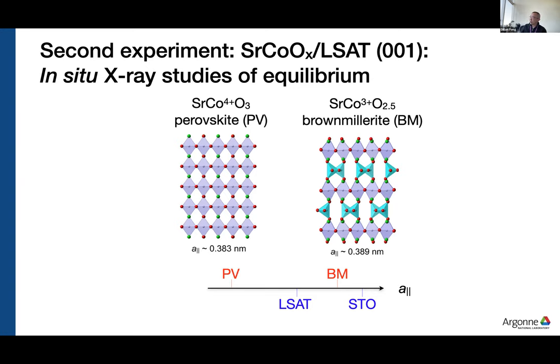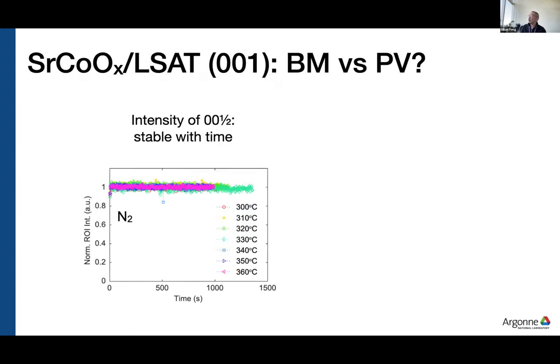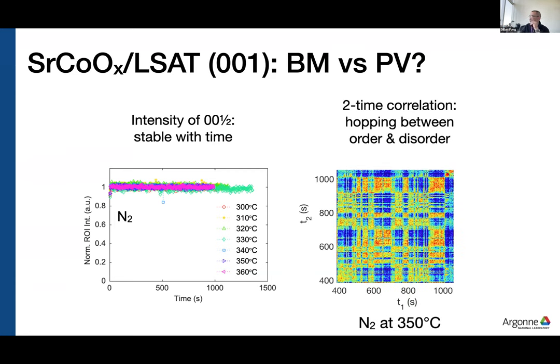But if you grow strontium cobalt oxide on LSAT, it's sort of sitting in between the perovskite and the Brownmillerite, which makes it more interesting. So if I were to plot the intensity of the 0.5 peak again, we can see that it's fairly stable with time. So this is the 0.5 for these different temperatures from 300 to 360 Celsius, all in nitrogen. But although the intensity is stable, if we plot the XPCS, the two-time correlation function, we see that it's fluctuating like crazy, okay? And so it's hopping between ordered and disordered states. And this was taken at 350 in nitrogen.